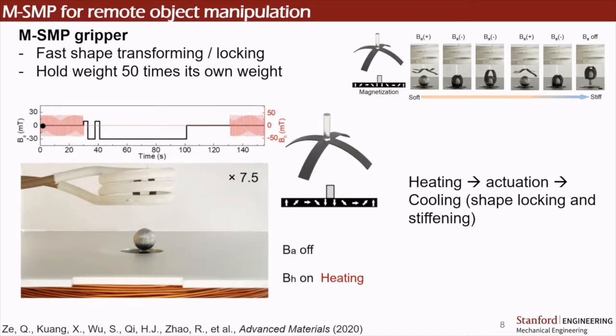But in terms of functionality, if we look at this soft gripper, this is made of magnetic shape memory polymer. When we heat it up, it becomes really soft, just like whatever other soft materials. Now we are trying to grab this very heavy ball. It doesn't do it because it's too soft. It does not provide enough driving force. But now we can easily tune the rigidity through temperature manipulation. Once it's at room temperature, it becomes really stiff, and now we can successfully lift this object. Then by increasing the temperature again by induction heating, it can let go of this object.